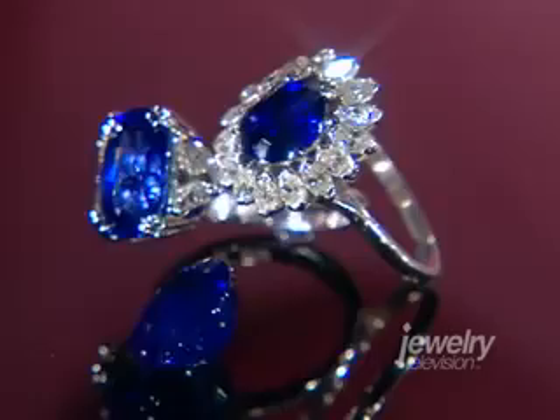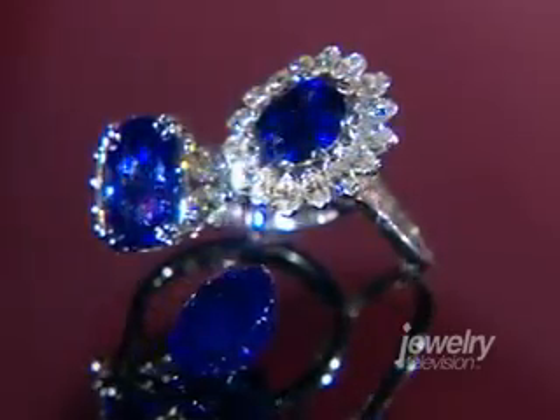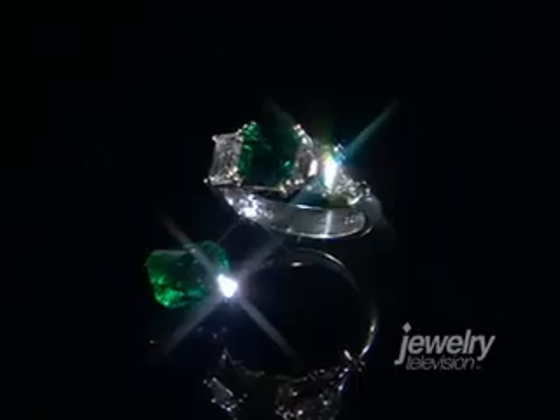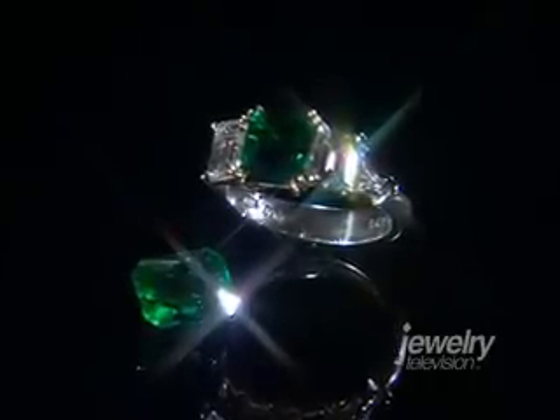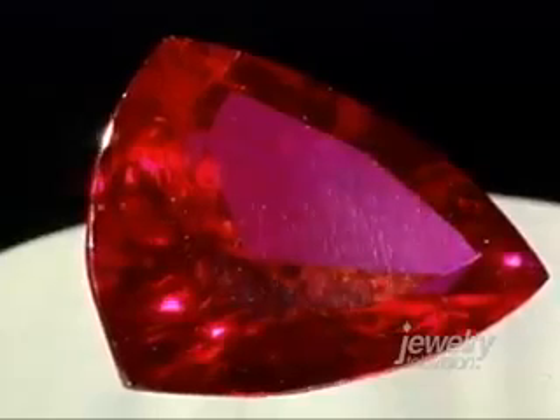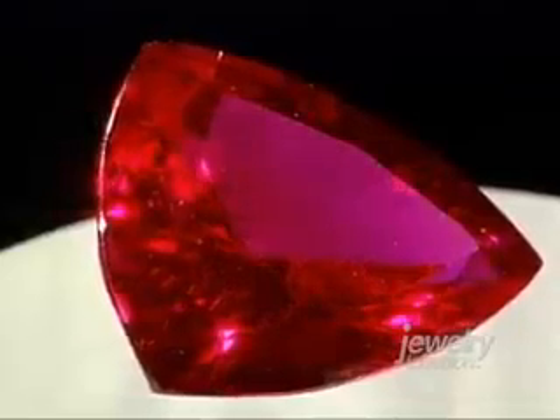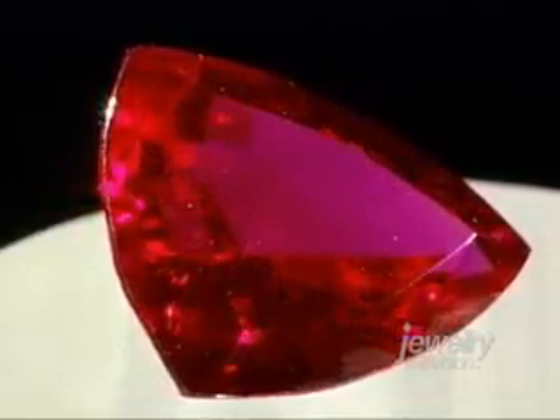The inclusions will heat up and expand at a different rate than the ruby or the sapphire that holds them. And that may cause the inclusions to open up fractures within the ruby. Although heat treatment of gemstones is common practice, it can affect price and should always be disclosed at the point of sale. Fine quality, untreated sapphires, rubies, and emeralds are very rare, command much higher prices, and should always come with a gem testing report.